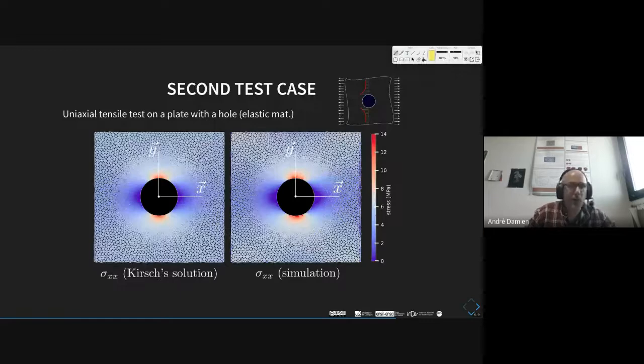So here, this is a qualitative study. You have a plate with a central hole, and this is only a tensile test on this sample. And here, as you can see, this is the stress. You get a stress concentration around the hole. Here is the analytical Kirsch solution, and here are our simulations. As you can see, it gives quite similar results, so it seems to be accurate. We get some main differences just very near the hole, so maybe we are not very good just near the boundary condition, in fact the free boundary condition.